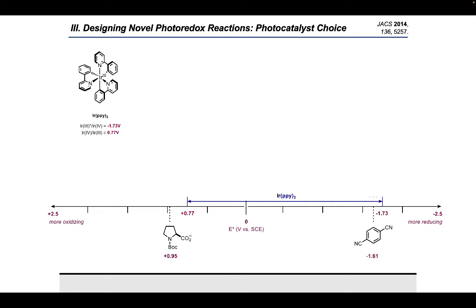On the chart at the bottom, I've also marked out the oxidation and reduction potentials of N-Boc proline and the 1,4-dicyanobenzene substrates respectively. So you'll see that while the excited state photocatalyst has a reduction potential of negative 1.73 and is thermodynamically favored to reduce the dicyanoarene at negative 1.61 volts, the same is not true over here with the oxidation of the N-Boc proline substrate. Here the oxidation potential of plus 0.77 volts is endothermic relative to the substrate. So we need a catalyst that is as reducing as iridium PPY3, but more oxidizing.